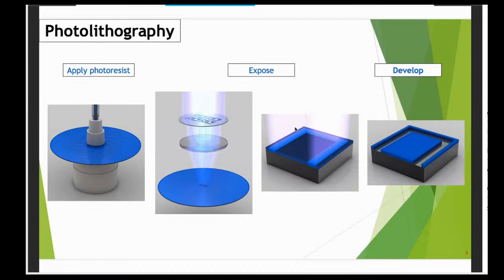So here in the semiconductor industry, you take a wafer and you apply resist on it. Photoresist is a kind of organic material that is sensitive to light. Then you have masks, right, which can hide a certain area and expose the other areas on the wafer, which is coated with a photoresist. So you take the mask and you take light, most likely ultraviolet light, and you shine that light through the mask onto the wafer that is coated with the resist. You expose certain areas of the wafer, and depending on the nature of the material we have coated on the wafer, when we develop them, the exposed areas can either be etched out, or the areas that were not exposed can be removed. So it goes both ways, all right?